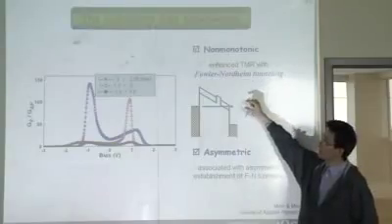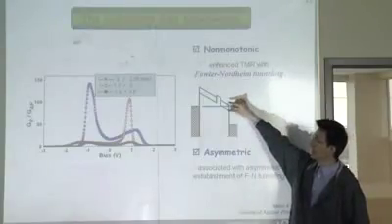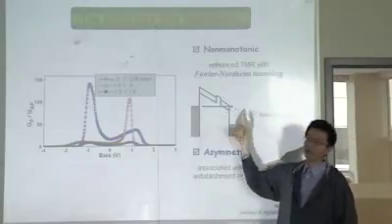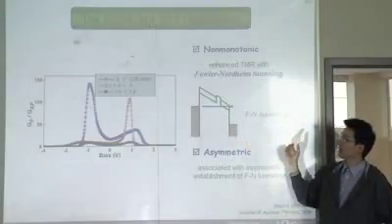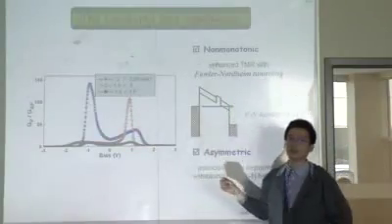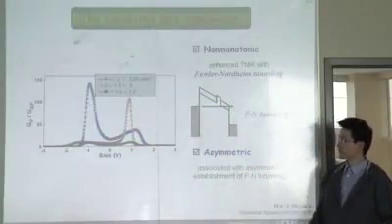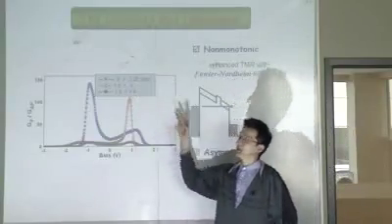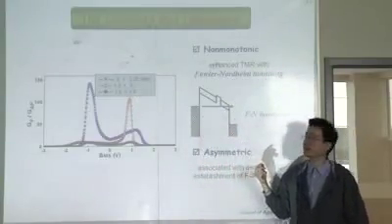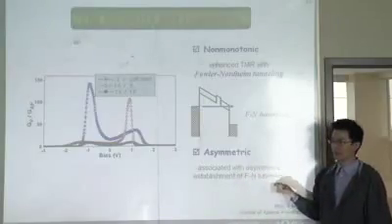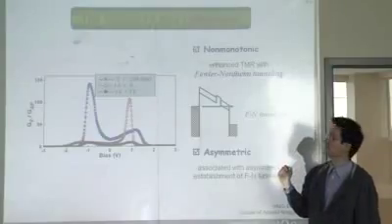In our situation, we have a spin filter. The spin up and spin down channels will establish Fowler-Nordheim tunneling at different voltages. As a result, we see this significant difference in the magnetoresistance. The asymmetric behavior is clearly associated with the asymmetry of the tunnel barriers, and it can be explained by the asymmetric establishment of Fowler-Nordheim tunneling.